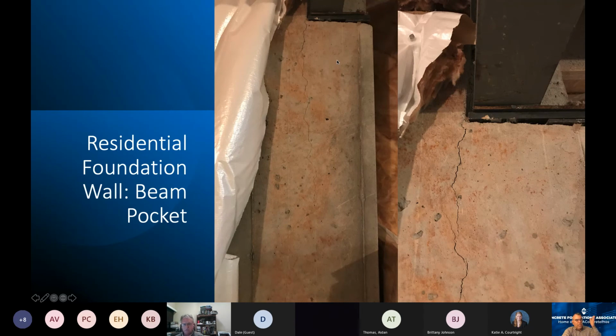In actuality, what's happened here, because this particular case is on a wall turn, so the wall is coming in from the left, turning and receding away from us in plane with the steel beam, but the load of that steel beam is putting enough force into this section of the concrete directly underneath it that as the concrete wall to the left is shrinking, and this is really hard, this is probably one of the hardest places to put reentrant bar corner reinforcement, there's no steel in here reinforcing this, and so it can't help but to shrink and crack.